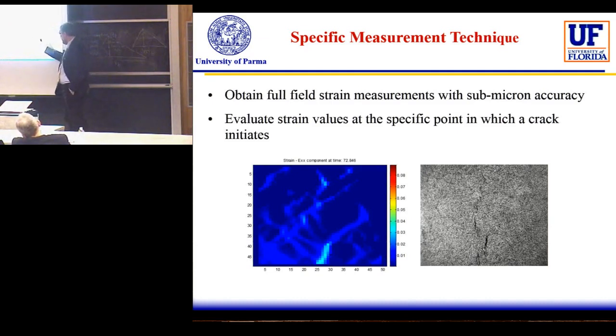based on grayscale analysis. The basic concept is that one pixel has one specific level of grayscale. If the area, the so-called area of interest, is sufficiently small, and we find the same grayscale in 2 pictures, we can make the hypothesis that it's the same pixel that changed position. Of course, the more you increase the area, the higher the probability of finding similar grayscale, and the accuracy of your measurement goes down.